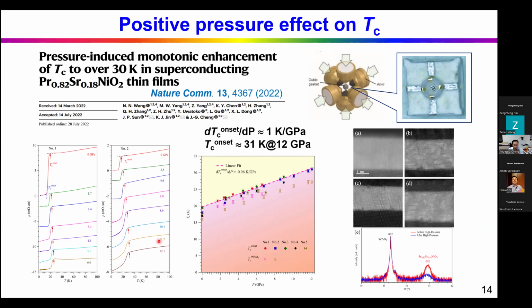To figure out what's going on here, we performed TEM measurement and XRD after we decompressed the pressure cell and took the sample out. We found that under pressure it produces a lot of structural disorder. This is before compression, and this is after compression, with a lot of structural disorder. The main phase is still the 112 phase, but it becomes very broad. This blue one is after compression.